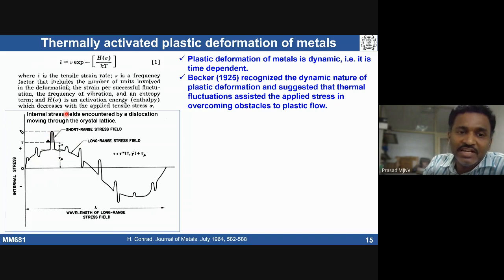Assume that in a material I have some long range stress fields and also short range fields. So the total stress required to overcome, that means to initiate plastic deformation in the material, I need to apply a tau naught stress. Then only do I see plastic deformation taking place. Out of tau naught, tau mu is basically the stress required to overcome athermal barriers.